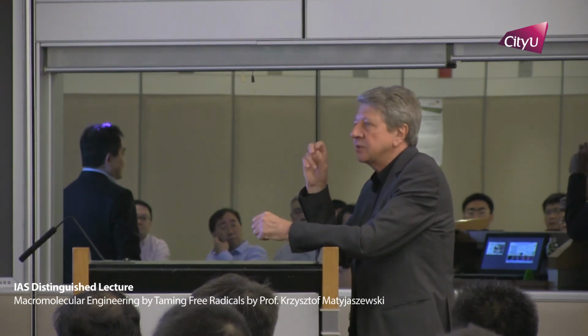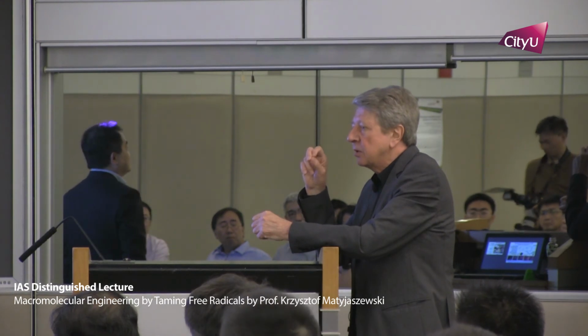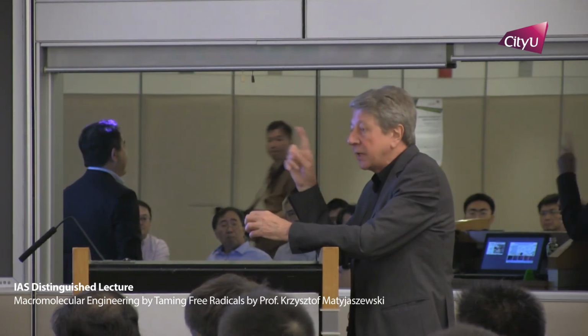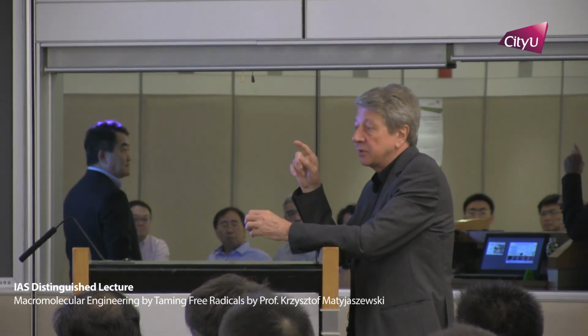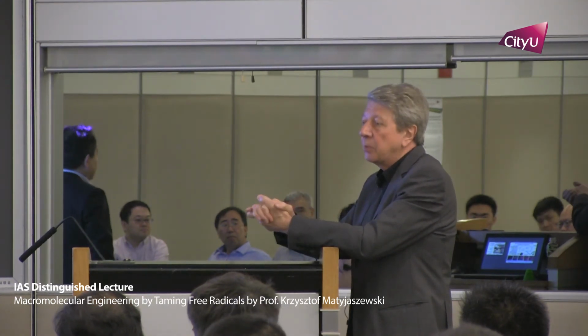You have, however, to realize what potential side reactions you may have. I mentioned to you that all of these systems are also dependent on a redox potential. So you can reduce or oxidize not only catalysts, but potentially also radicals. Radicals have a redox potential for acrylates around negative 600 millivolts, but for styrene negative 1 volt, which means you open the window much more. But there will always be the possibility that this electron transfer may happen. And even if you pass radicals, you also have monomers. Monomers can also be reduced. So for some systems which are very delocalized, you have to look at their redox properties, both reduction and oxidation, and whether you are in a window in which you can really operate.